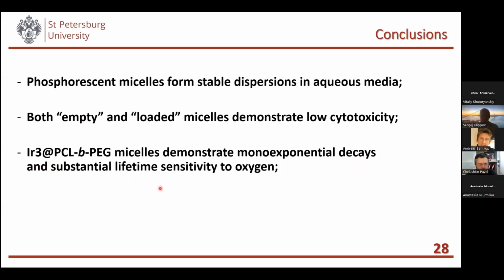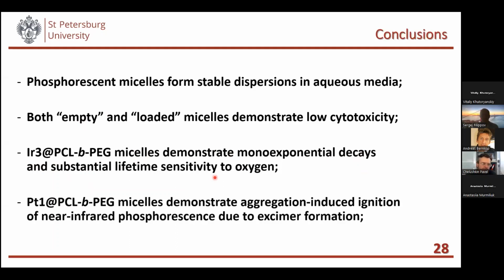Of course, we would like to have higher sensitivity here. We would like to see not twofold, but 3 to 5-fold difference between oxygenated and degassed lifetimes, but now we have only a twofold difference. And also we found one system that demonstrates aggregation-induced ignition in near-infrared phosphorescence.